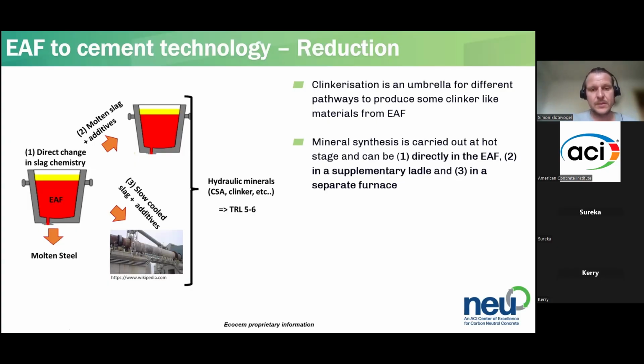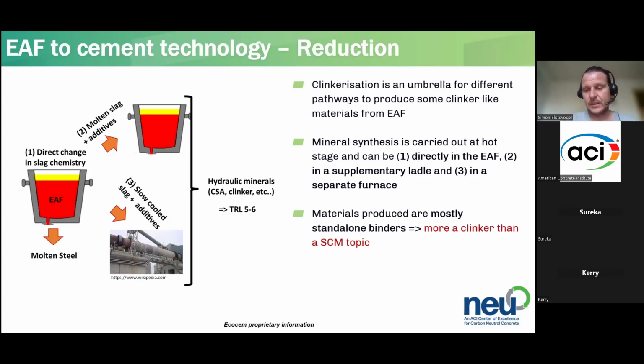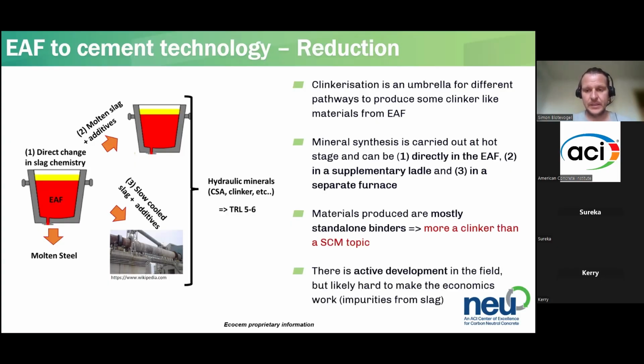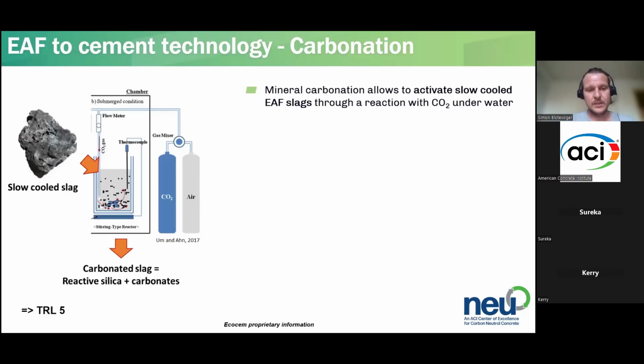And as slag is the waste bin of steelmaking industry, there are many impurities which might not result in a perfect clinker. And also if you're using the electric process coming from a melt would yield a slightly different crystallography of the cement. So this is clearly more a clinker topic than an SCM topic, and I will not go much further into that, but that is one option that is clearly on the table. And there's active development, and there might be something coming out, but the TRL at the moment is clearly lower than of granulation technology. And the last one is mineral carbonation.